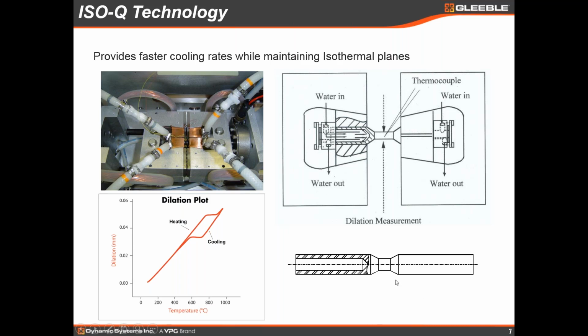If you look at the lower right of this sample, you see a cross section of an IsoQ sample, and it has two hollow ends. The measurement center is solid, but each end is hollow, and we're able to inject coolant, either air or water, into this hollow end, and this is on both sides, although only one side of the sample is shown cut away. We can inject quenching fluid into both sides of the sample.